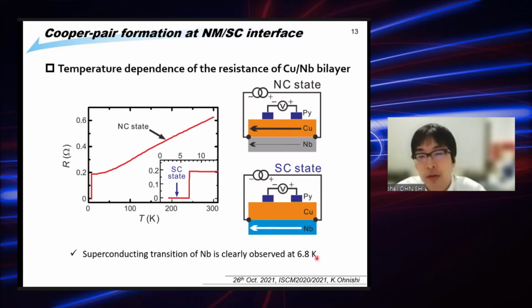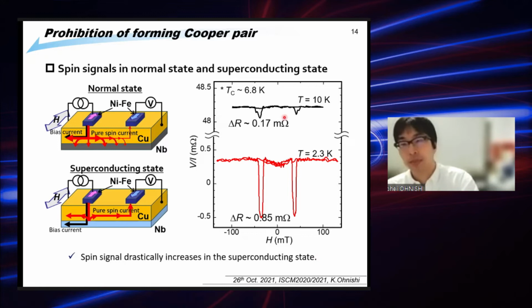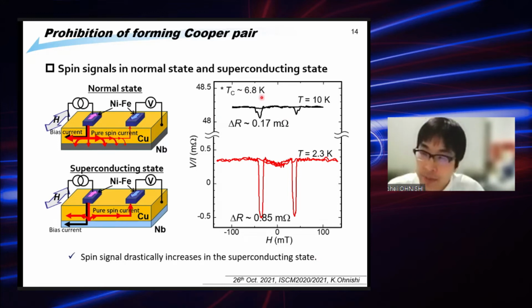So we measure the spin signals above and below 6.8 Kelvin. At 10 Kelvin, this is in the normal conducting state. In the normal conducting state, the spin signal is very small, 0.17 milliohm.